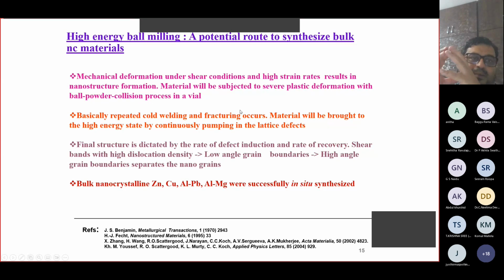So in ball milling, what happens is that you will have a small container, and in that you put balls and also powder particles of your interest, then close it and subject it to some kind of shaking. As a result, these balls impinge or bombard your powder particles. So your powder particles get entrapped between two balls or between the container inner surface and the ball.